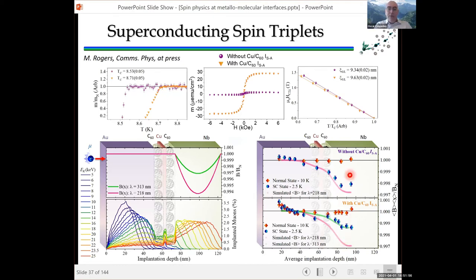But if you introduce the copper C60 interface, that diamagnetic effect is partly suppressed. So that change in the local magnetic field is still negative, but not quite as negative as it was before without the copper. If we use a multiprobe layer, then we can see that we can even detect both the suppression of the diamagnetic effect, and we can also detect the paramagnetic Meissner effect in the gold layer above the